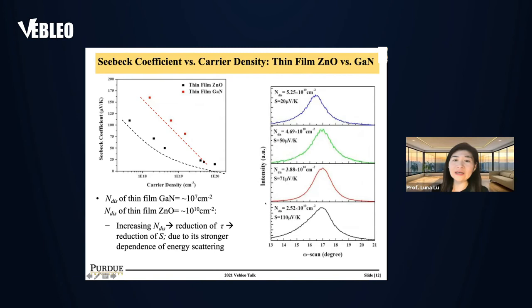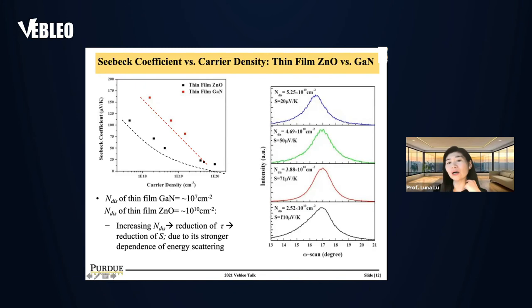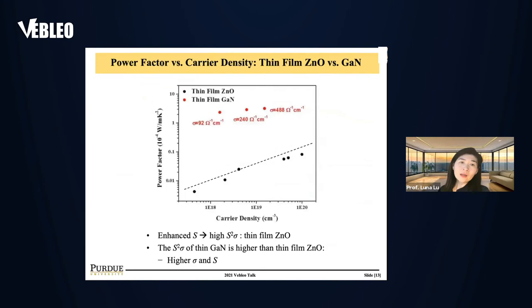This is further validated by X-ray diffraction characterization. The omega-2theta scan clearly shows dislocation density. Keeping dislocation density at 10^10, we observed Seebeck coefficients ranging from 20 to 110 microvolts per Kelvin, with drastically reduced full-width at half-maximum and increased film quality of zinc oxide. As expected, power factor has been drastically increased with carrier density — which is very good news, as increased carrier density enables higher power output.